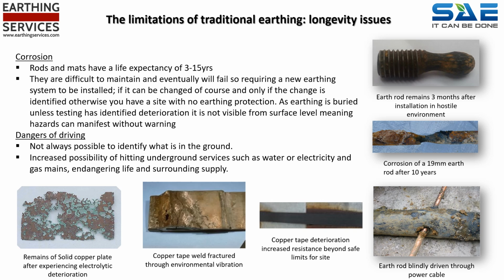Here we see some pictures of corroded earthing materials from earth mats to earth rods. It is worth noting that the corroded rod down to the thread is the remains of a 1.2 metre UL approved copper bond rod after just 3 months in an area of saltwater migration and subject to frequent low level discharges. The quality of the rod is not in question. It was manufactured to the highest standard in the world by the leading manufacturer. The problem is the product itself.